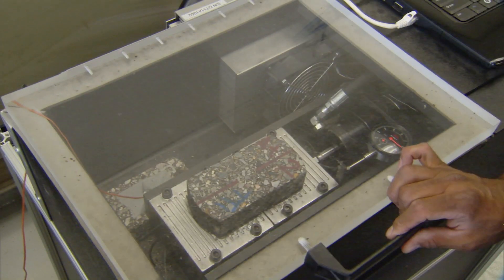We didn't just do volumetric density design. We actually put in a cracking and a rutting performance test and tried to balance the performance while also balancing economics and still getting that density. We focus not just on rutting — we are also focusing on the cracking. That's the term 'balanced mix design.' We're going to look at cracking, and we started doing cracking tests, which was the overlay test.